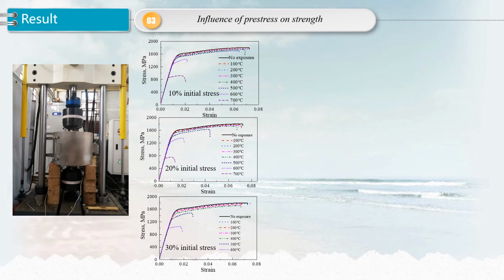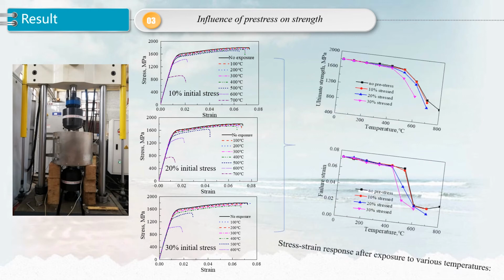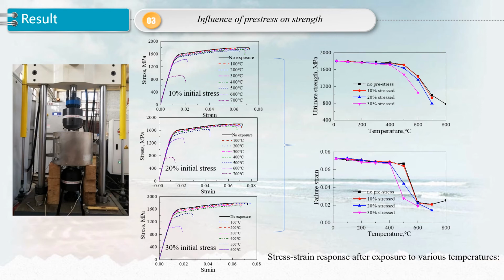The stress strain curves of specimens tested under different stress conditions and temperature are shown in the middle figure, where the overall stress strain response of specimens was similar until 400 degrees centigrade, no matter how high the pre-stress was. The variation of strength under 10% pre-stress was nearly the same as one without pre-stress. It dropped slightly for specimens under 20% pre-stress when the temperature was above 400 degrees centigrade. A remarkable strength reduction was found when the pre-stress increased to 30%.